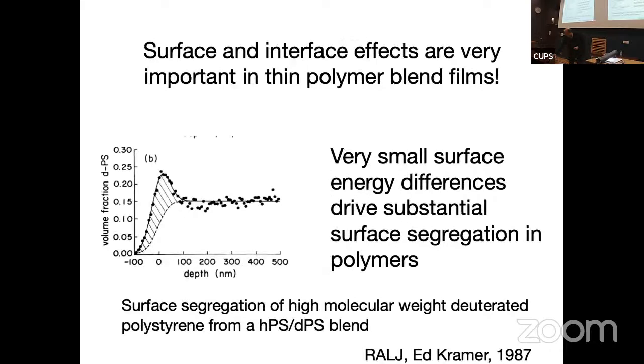First of all, these surface and interface effects are very important in polymers. And this is, again, a strange feature of polymers. If I take any mixture of things that want to mix, you'll always find the surface will have the lower surface energy material at that surface, because that lowers the system's energy. So if you take a glass of gin, something that's like 40% alcohol, 60% water, the very surface of that will be almost all alcohol, because alcohol has a lower surface energy.